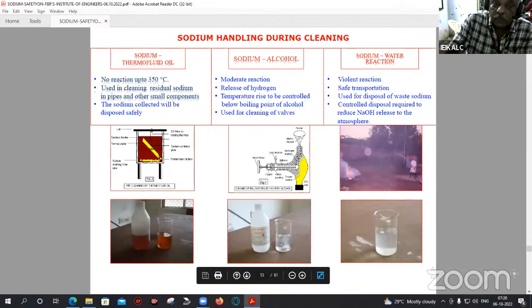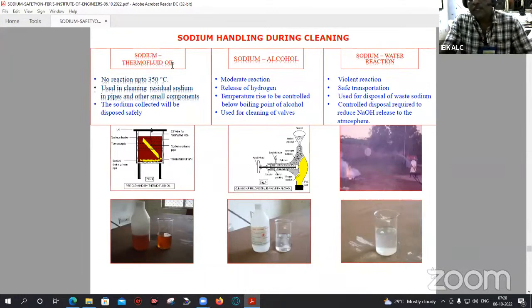And next, coming to handling sodium, suppose we are going for any maintenance requirement, or we need to replace components. We need to cut the components to remove them. For that, there are certain methods by which we clean the removed components. This is one way, where the pipelines which are filled with sodium can be put in a thermofluid oil bath at a higher temperature of 150 degrees centigrade. The sodium goes into the oil. This oil is an organic oil. It doesn't react with sodium and is inert towards it. So thermofluid oil is one.